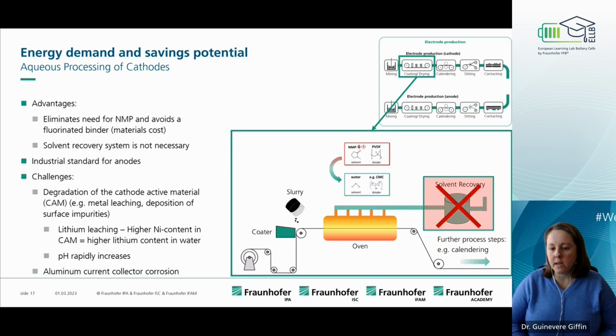So what I'm going to do now is I'm basically going to go through at least a couple of these options. So in terms of aqueous processing, the big advantage is you eliminate the need for NMP, or basically you would substitute NMP with water as a solvent. This also avoids the use of a fluorinated binder. So in terms of materials cost, this would be replaced by something like carboxymethyl cellulose or, for example, SBR, which is a latex type binder. Of course, other binder systems would be possible. And therefore, by moving to water, you don't need the solvent recovery system. And an aqueous process is already an industrial standard for anodes.